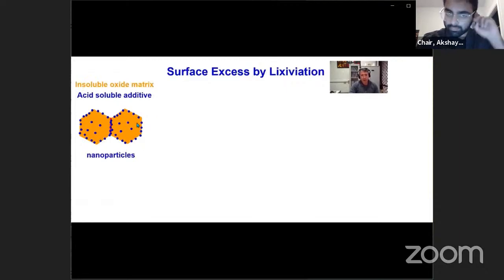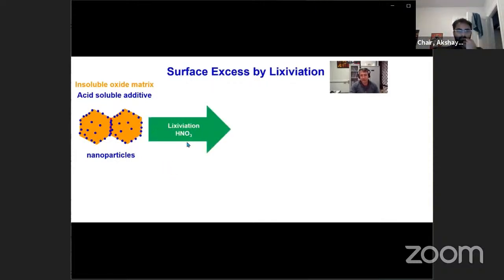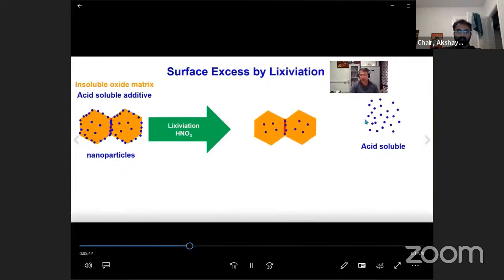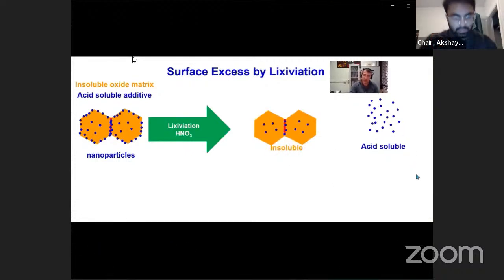Some years ago, we proposed a method to know the surface excess by a selective leaching method. For nanoparticles, grain boundaries and surfaces, we have an additive that segregates on the surface and the grain boundary, and some additive soluble in the bulk. Then we have an insoluble oxide matrix, and the additive is soluble in acid solution. Then by leaching in nitric acid, for example, it's possible to separate the atoms segregated on the surface from the atoms in the grain boundary and soluble in the bulk. This part is insoluble, this part is acid soluble.